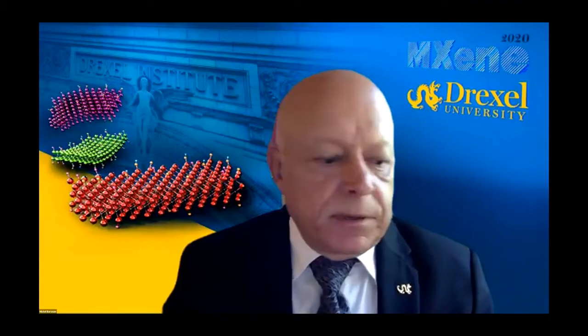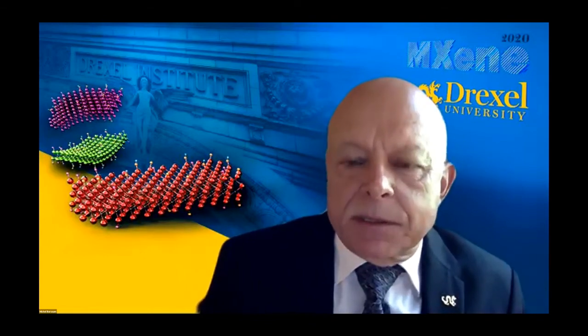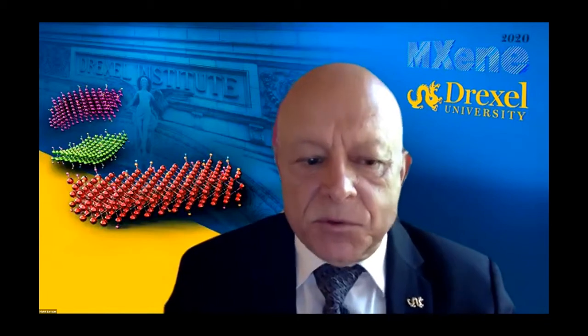And then in the early 90s, Pampuch and coworkers in Poland started trying to make titanium silicon carbide, and they came close, but their samples were not that clean. Then in 1996, our paper on titanium silicon carbide was published, and in that one, we showed that these materials really have remarkable properties. And in 1999, we discovered the first prototype of the 413. That's when I decided to call these phases MAX phases. And then in 2011, we discovered MXene with Yury Gogotsi and Michael Naguib. The first generation was HF etched, the second generation in 2014 was non-HF etched, and that was important in terms of popularity of the material, as I'm going to discuss in a minute.